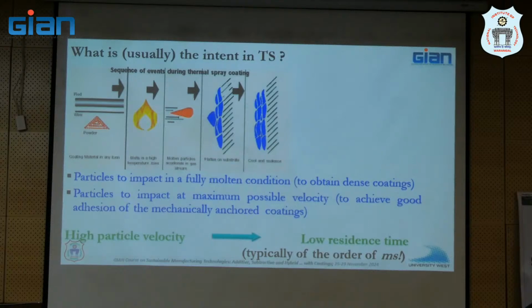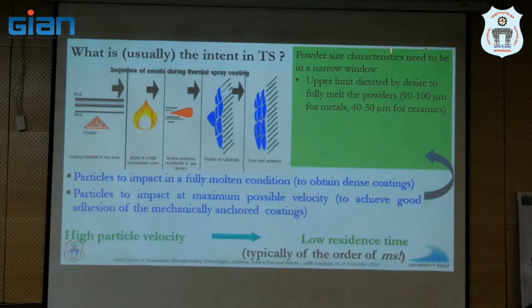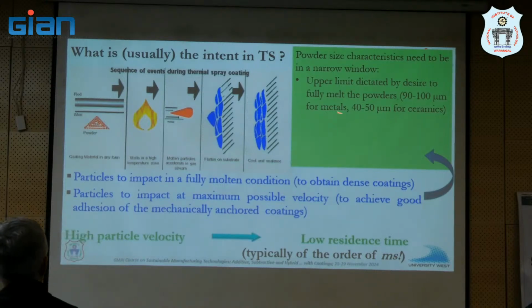That residence time is of the order of milliseconds, yeah? So all action has to happen in millisecond time, correct? What does that do? It imposes an upper limit on your particle size, correct? So you need to pick your particle size such that in that millisecond residence time, it will fully melt, correct? So this is easy to imagine, right? For that reason, your particles need to be below a certain size, right?